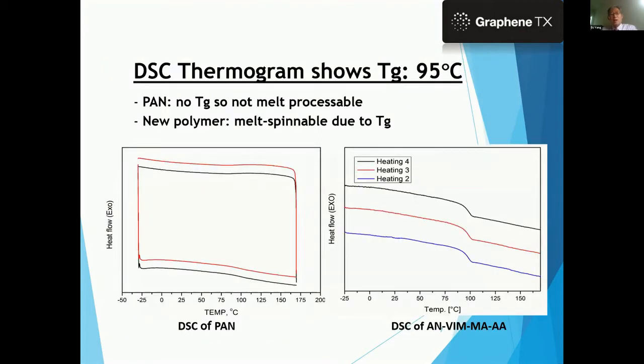Then you may ask why it is melt spinnable? Because we developed the technology to create a so-called glass transition temperature. The regular copolymer PAN or PAN polymer they are using doesn't have a Tg. But as you can see here, it's reproducible, and we have a glass transition temperature at 95 degrees C. So we have 2 different phases. So that's why we will be able to melt spin.